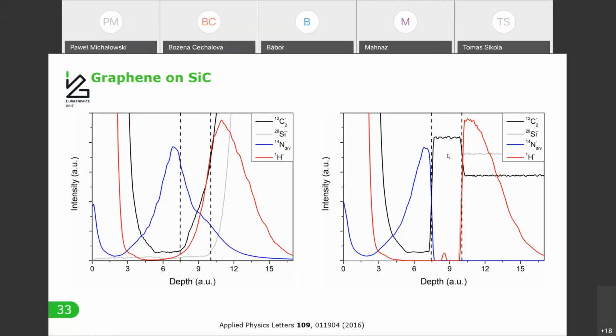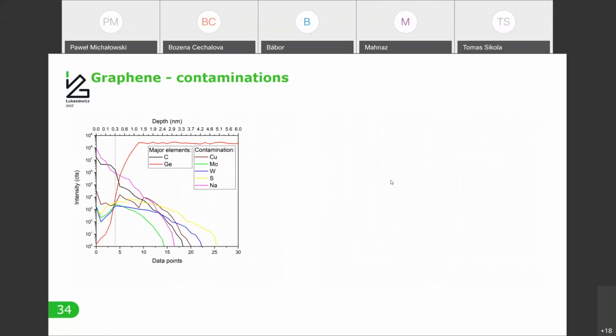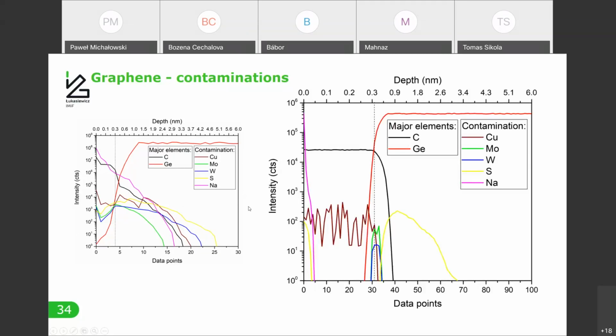So with such a precision, we also try to use it for detection of contaminants, and also compare the standard one. This is graphene grown on germanium, where the reactor itself was a little bit contaminated because other materials were used. So here it's really difficult. In carbon, we can see that the carbon is decreasing, so probably graphene is somewhere here. Here the germanium is increasing. All of these contaminants can be detected, but not much can be said where precisely they are located. But again, with the enhanced results, we can do it.